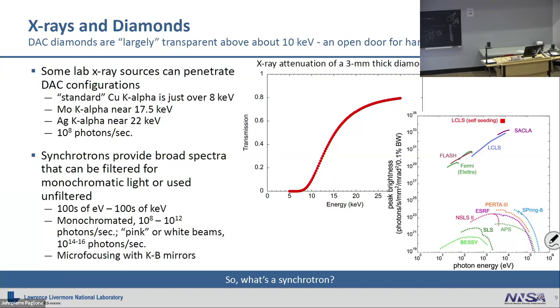So you can see if you're down here at your lab source that's under 10 kilovolts, your diamond on the way in, you've got two of them, remember, you have to go in and you have to come out. So your first trip, you've attenuated 90% of your beam just to get to the sample. Now you're going to attenuate 90% more as it goes out. So you quickly lose a lot of your photons down here at most lab sources.